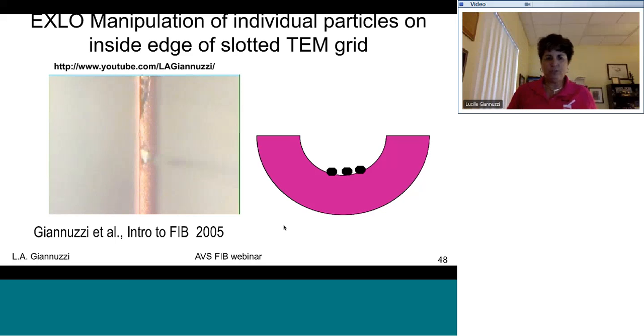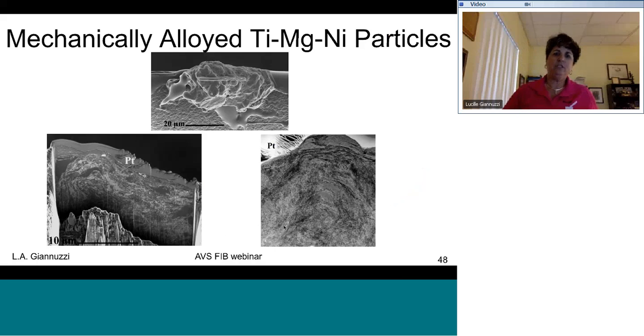Okay, so once you've got particles on the grid, then you can go ahead and straight away mill it, so it makes it much easier and much less dead time. So there's your glue, there's your particle on the glue, there's your platinum, there's a FIB image of the sample, still about a micron thick, and then there's your subsequent ion going there, just this image.